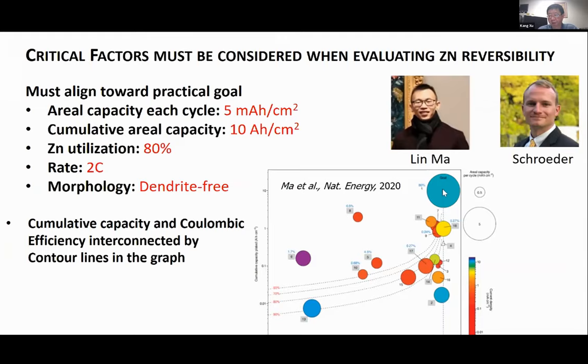But for this kind of application, we set a goal which is similar to the goal that the Paul Albertus group set for the lithium metal electrode. We want to have 2C rate, 80% utilization, and the cumulative area capacity should reach at least 10 amp hour per square centimeter. So from then on, we rigorously follow this standard protocol.